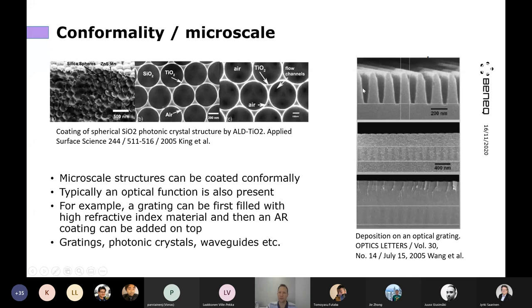And we start by introducing ALD that will actually fill the void completely. So in this next step, you can see the original structure. Now it's all filled with ALD film, and then also continued a little bit. We end up having a very smooth surface if we just continue ALD long enough on such a surface. And then on top of that, in this case, there's been also in the same reactor continued to deposit an anti-reflective coating on top. So a multi-layer AR coating has been deposited on top. So these are some of the examples on the micro scale.